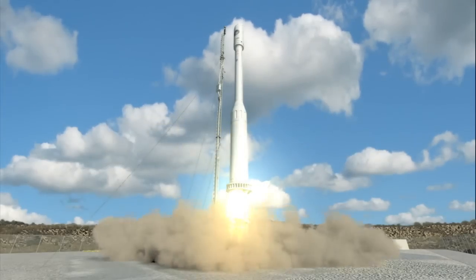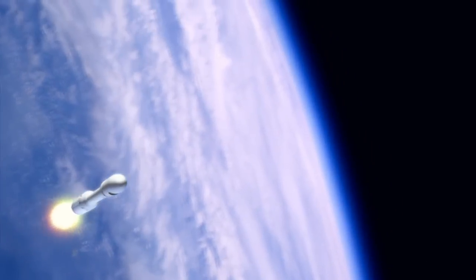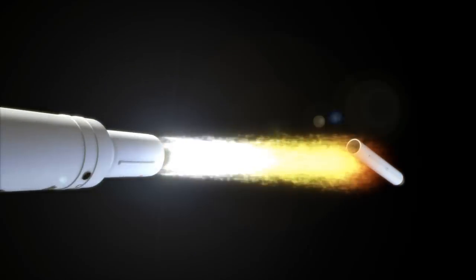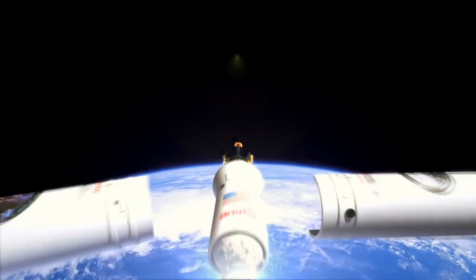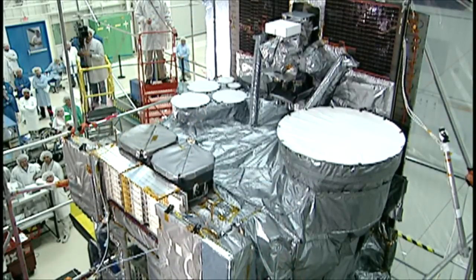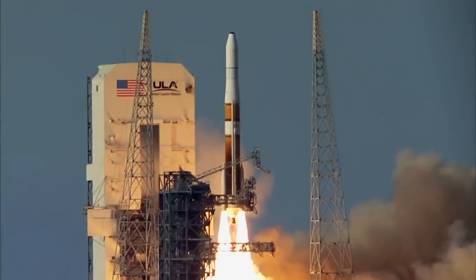And lift off. So when we prepare a new technology for spaceflight, we need to consider the different environments that technology is going to experience. If we're going to fly something in space, we can't have the nanotubes falling off and contaminating mirrors, so we had to make sure that they were very robust. We discovered that the adhesion layer is really the trick to getting the nanotubes to stick — now you have to scratch them off. We are interested in vibration testing for these carbon nanotubes to determine how well they adhere to the substrate and whether they will be liberated during launch.